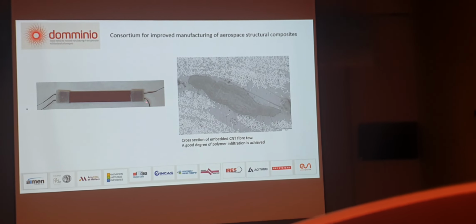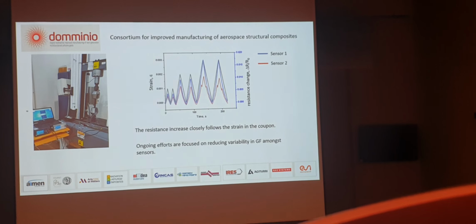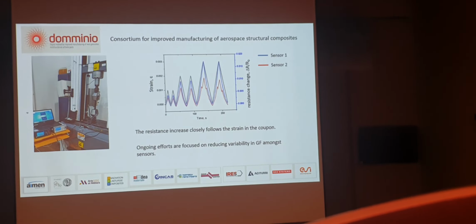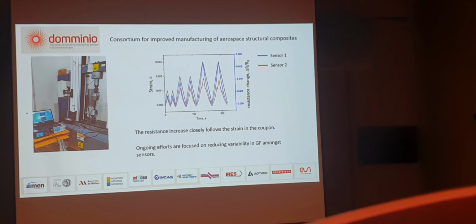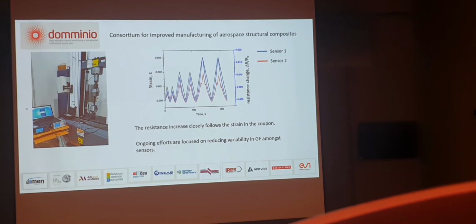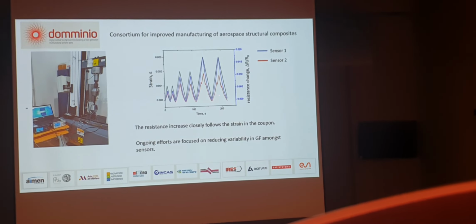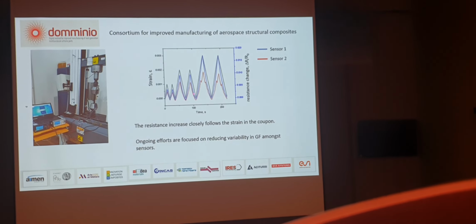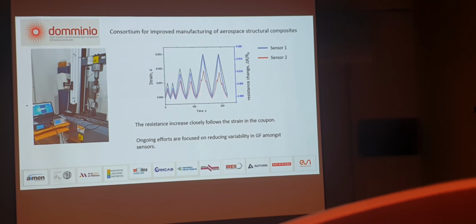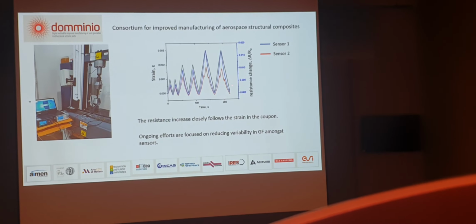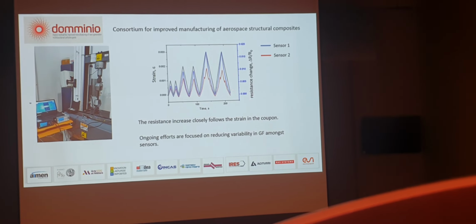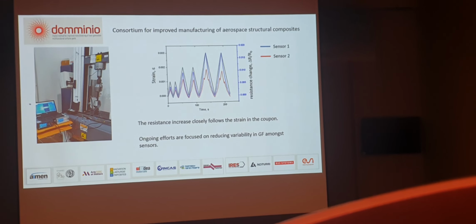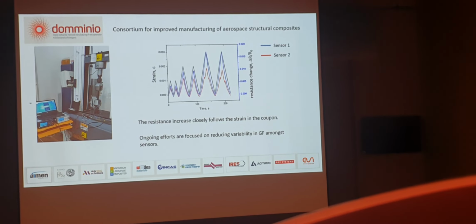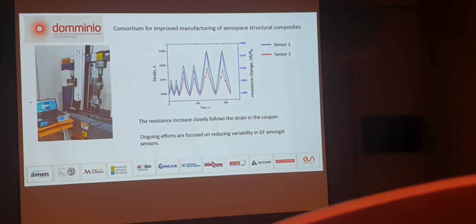So we put sensors, connect the cables, and the idea is, can we use this as a sensor? Of course, the answer is yes. We get a nice linear piezo-resistive signal, and we're working on trying to exploit that for simulation. Can we really start using this to detect damage and to simulate and so on? And truth be told, every now and again we get a bit of noise, and this is a challenge. We need to make them more reproducible, but I don't really see that as a big problem in the long run. Perhaps the biggest challenge is how do you localize damage and not just sense it, not just detect it.